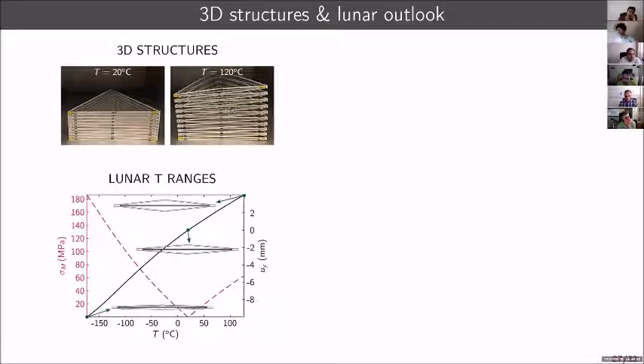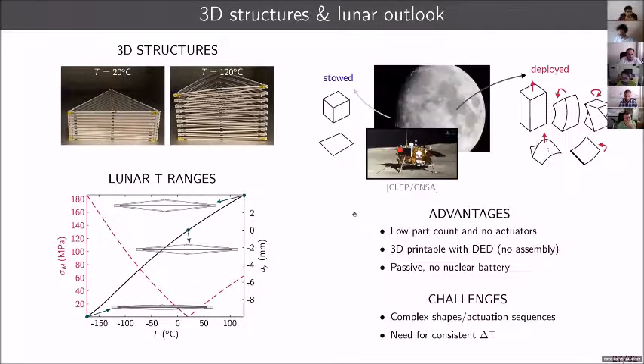We also applied this idea to the lunar temperature range, the temperature range that is up there on the moon. On the moon, during the night, you have temperatures of -170 Celsius, during the day, 130. So we wanted to create structures that can exploit this large temperature range without plastically deforming. We did that by creating this initially deformed structure, starting from our unit, and then testing numerically what would happen. We think the applicability of the structures, for example, to create passive actuation systems for lunar structures is quite interesting. There are problems, of course. For example, we didn't look at fatigue deformation. If there are day and night cycles, I'm pretty sure this would be a problem.